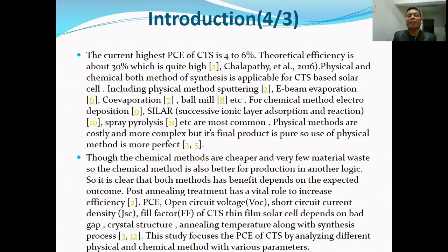Both physical and chemical synthesis methods are applicable for CTS-based solar cells. Physical methods include sputtering, e-beam evaporation, co-evaporation, ball milling, etc. For chemical methods, we use chemical bath deposition, SILAR, spray pyrolysis, etc. Physical methods are costly and more complex, but the product quality is better. Chemical methods are cheaper and produce very little material waste, so chemical methods are also good. So it is clear that both methods have benefits depending on the expected outcome.